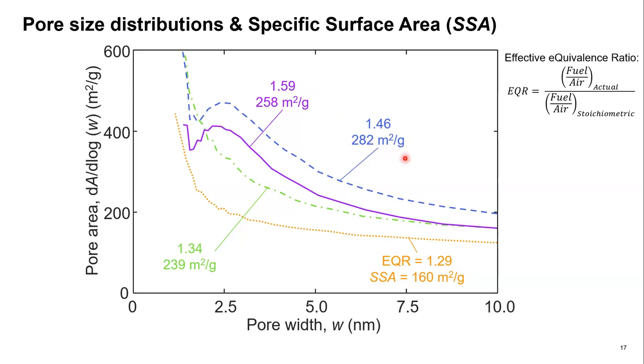So here we see that the specific surface area is increased by the presence of a small number of pores, because if you remember from before, all of these conditions produce soot with very similar primary particle sizes. And because of that, we would expect that if there were no pores, we would get exactly the same specific surface area. However, I will highlight that in all of these cases, this is a relatively small number of pores and that these specific surface areas are relatively low. So this tells us that in all cases, the particles are relatively non-porous. And without the high concentrations that I showed in the last slide, this data would not have been possible to obtain and we would have missed this nuance.